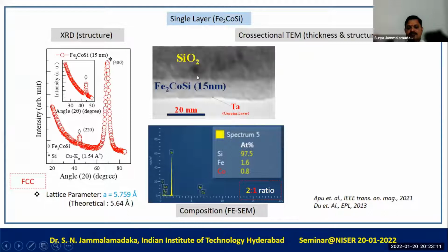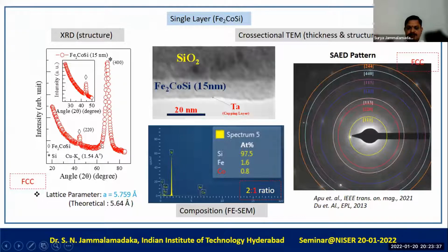We also looked at the cross-sectional transmission electron microscope images for measuring the thickness of the sample, and we could very clearly see the distinction between different layers. The composition of the material has been confirmed with energy dispersive X-ray spectroscopy. We could see the exact composition of Fe2CoSi. Also, to understand the microstructure or diffraction at the nanoscale, we did the SAED pattern, the SAED rings. What we could see is diffraction rings corresponding to Fe2CoSi. From this, we confirm that indeed our films are crystalline in nature, and the space group corresponds to Fe2CoSi.